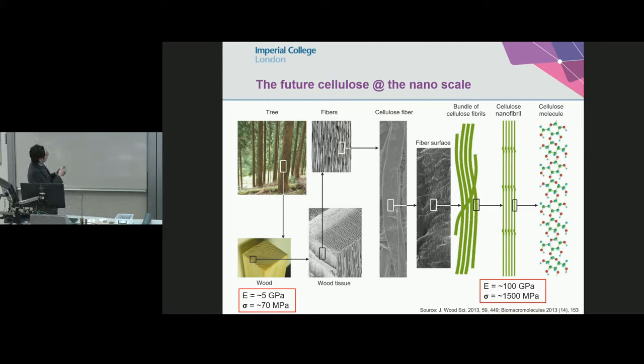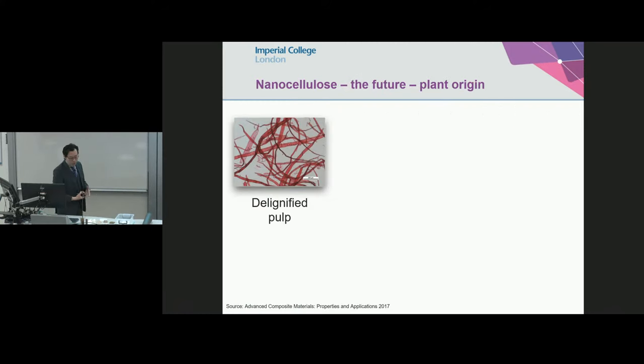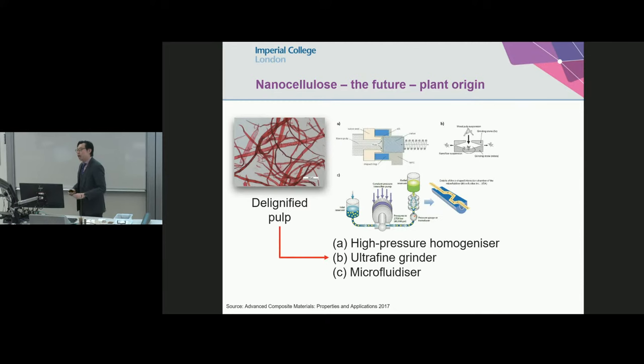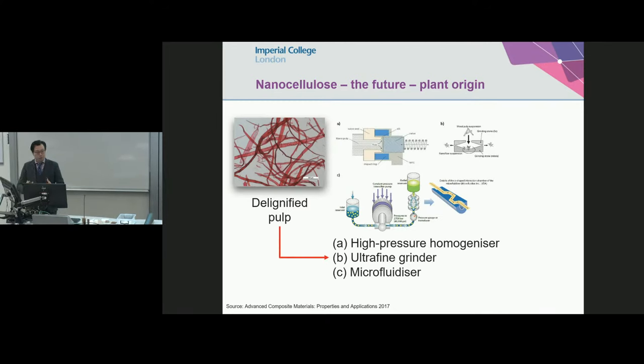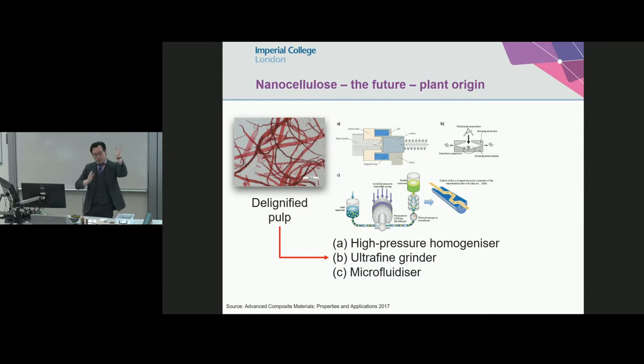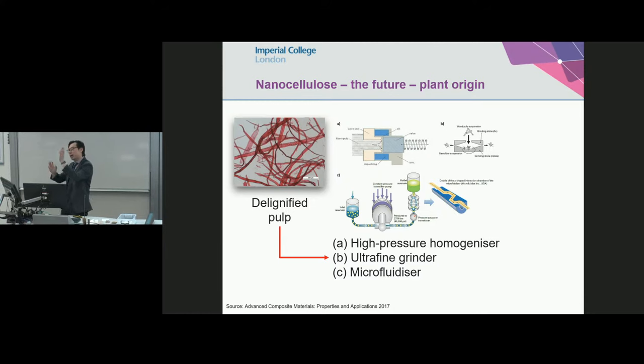Wood, we know we can pulp it, and we get these fibers at the micron scale. We know how to do that. We can easily get the cellulose molecules out. To get to this intermediate scale, you take pulp, which you delignify, these white cellulose fibers. You put it through high-pressure homogenizers, grinders, fluidizers. What it actually does is that the micrometer-sized fibers in these high-pressure systems are sheared apart, exposing the smaller fibrils. The smaller fibrils get sheared apart again, exposing even smaller fibrils, all the way down to the smallest possible building block, the cellulose nanofibrils.